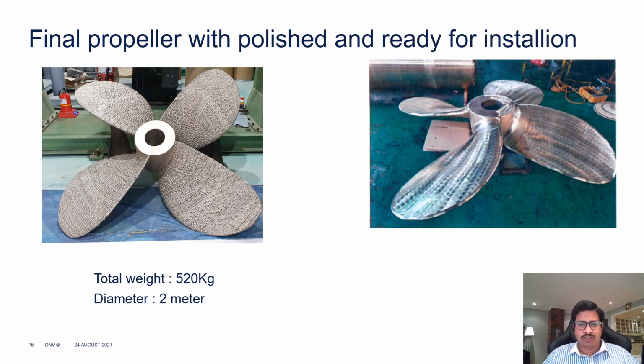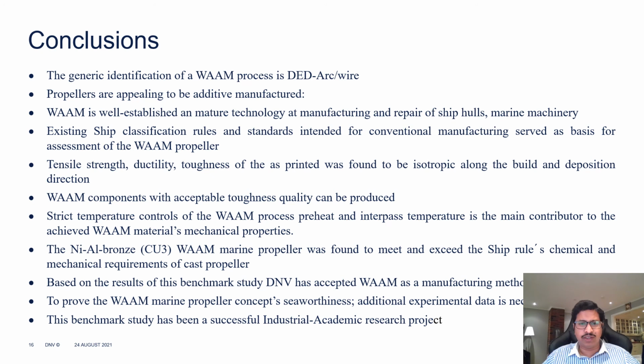So the final propeller weighed around 520 kilograms with a 2 meter diameter. It was polished and kept. So the conclusion of this is that the WAAM process can be used for manufacturing a propeller if all the parameters are strictly controlled and inspected. Tensile, ductility and toughness were found acceptable, and isotropy along the build and deposition direction was achieved. The toughness is also acceptable, achieving 27 joules and above, and it meets the requirement given in our DNV rules for ships.